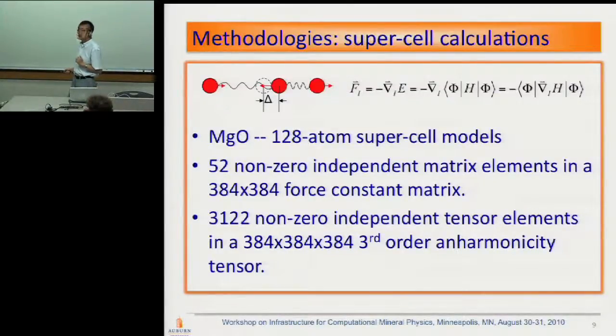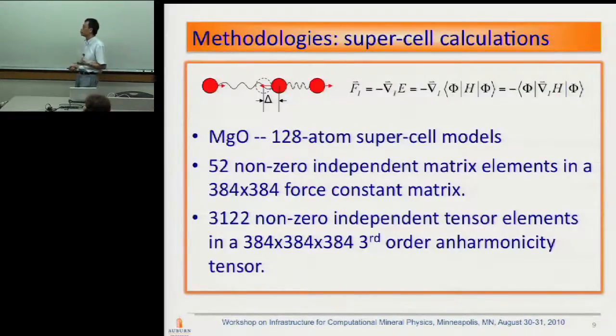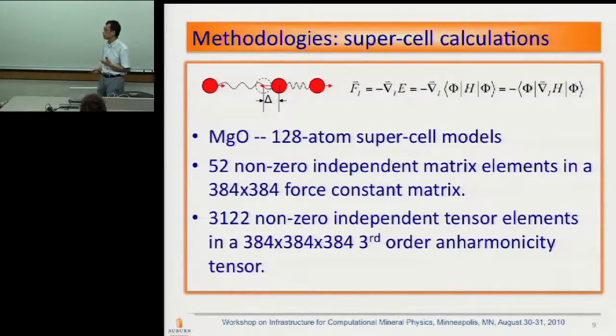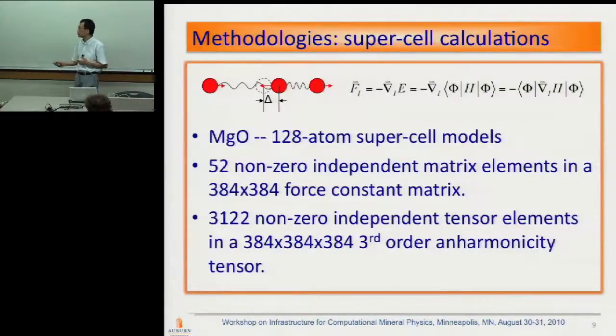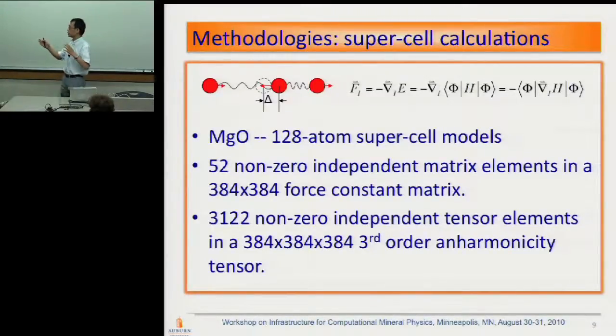For the MgO, it's relatively easy. For this calculation, when we do phonon calculation, we do a real space supercell calculation. We use 128 atoms and we use group theory to figure out the independent terms. So instead of doing a 400 by 400 force constant matrix, we figure out there's only 52 independent terms. We only calculate these 52 independent terms. The reason we use this supercell technique is because we can easily expand it to extract the third order lattice anharmonicity.